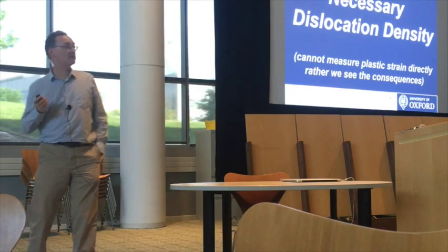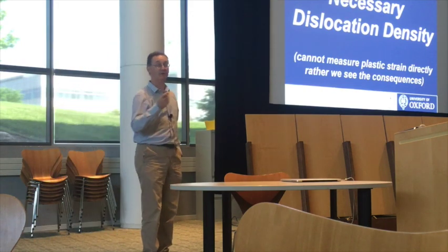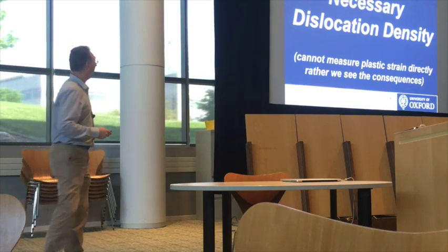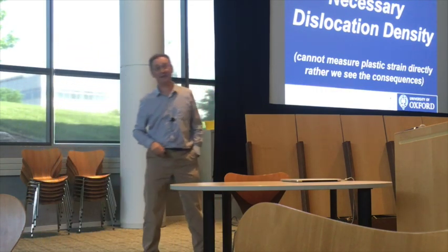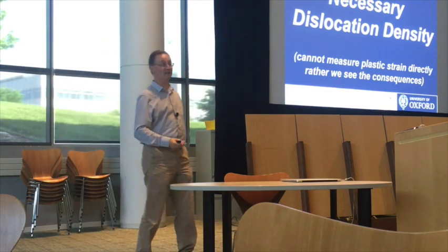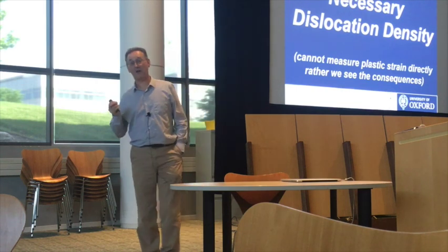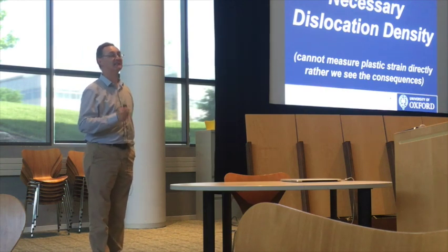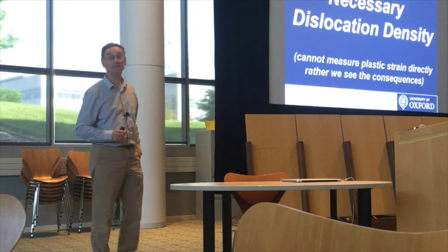So all I've talked about there is all about lattice strains, and therefore, if you know the elastic constants, stresses. What about plasticity? And this message at the bottom here in brackets, I probably should have put at the top in red letters or something, it's really important. It's a diffraction technique. You will not learn about plastic strains. A diffraction technique will tell you about the lattice, and that's a lattice strain and therefore an elastic strain.